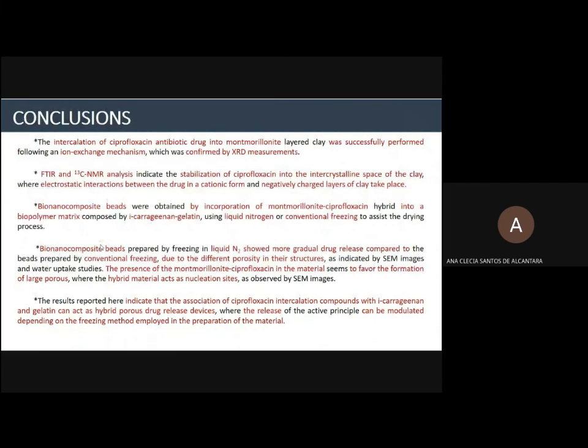The conclusions of this work: the intercalation of the ciprofloxacin antibiotic drug into montmorillonite was carried out by an ion exchange mechanism, which was confirmed by XRD measurements. Spectroscopic analysis indicates the stabilization of ciprofloxacin in the interlayer space of the clay, where electrostatic interactions take place between the cationic form of the drug and the negatively charged layers of the clay. Bionanocomposite beads were obtained by incorporation of the montmorillonite-ciprofloxacin hybrid into a biopolymer matrix composed of iota-carrageenan and gelatin, using liquid nitrogen or conventional freezing to assist the drying process.